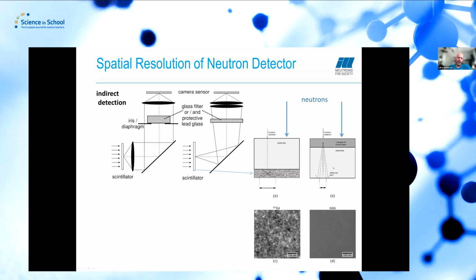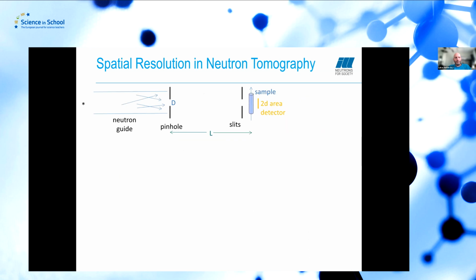You observe then the scintillation processes via the substrate here. So you can have then secondary effects also. Here you can have, for instance, multiple reflections between the two insides of the substrate. Here on the powder screens, you have scattering taking place in between the powder particles. And so normally, if you want to go to high resolution, like 5 microns, you don't want to have powder particles larger than that. And the general thickness of the screen also in the order of some microns then.